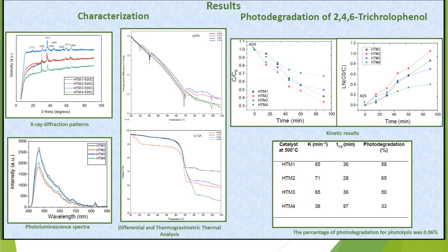And this figure shows the adjustment of the kinetic model of the relative degradation rate of 80 ppm of 2,4,6-trichlorophenol with the different catalysts, which corresponds in all cases to a degradation behavior of pseudo-first order, considering the steady state condition corresponding to the kinetic model of Langmuir-Hinshelwood.